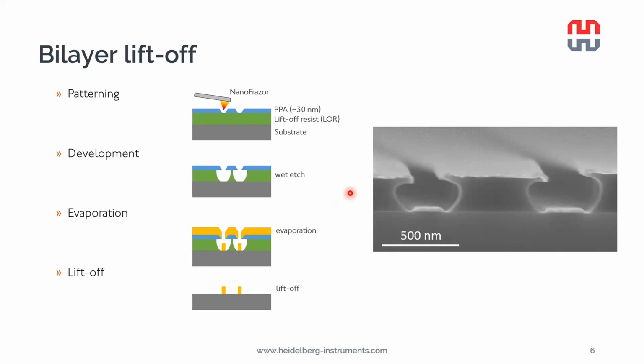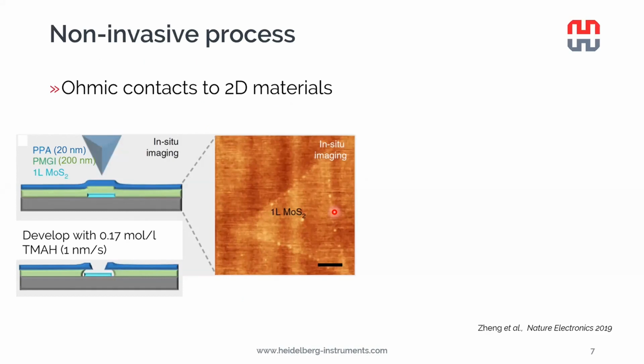In this SEM image, we see a cross-section of a bilayer lift-off sample just after the evaporation of the metal, and here we can indeed see that the metal is discontinuous between the bottom and top of the resist. We also see the freestanding PPA film and a nice undercut that has been formed in the lift-off resist. Now, this kind of bilayer lift-off process can be applied to virtually any patterns you wish to transfer on your sample. It's particularly useful for example, creating ohmic contacts to 2D materials, talking about electrodes or straight electrodes, for example.